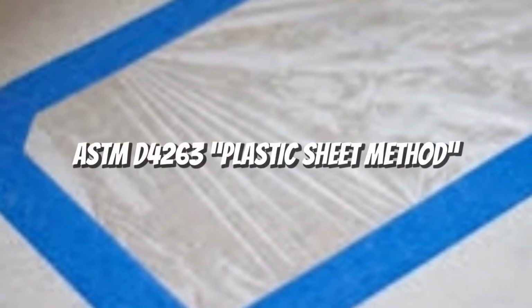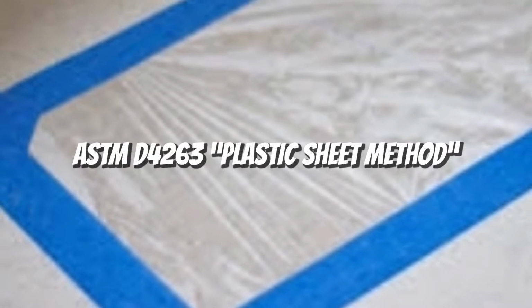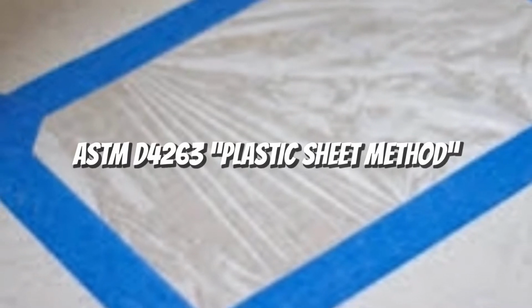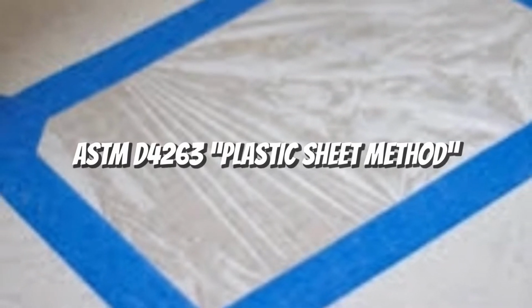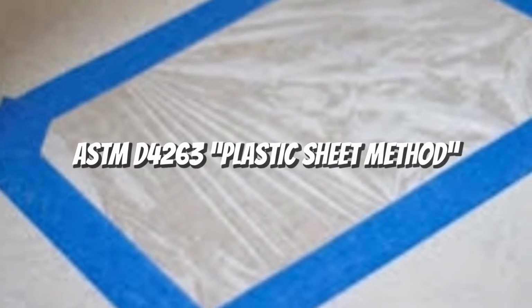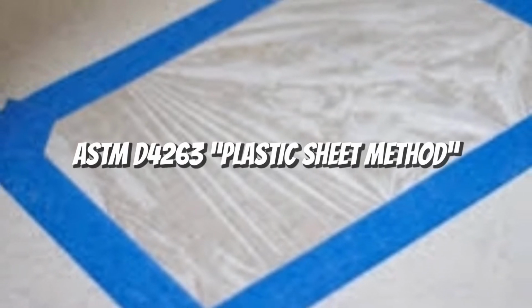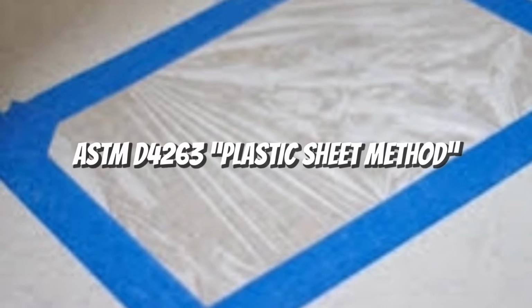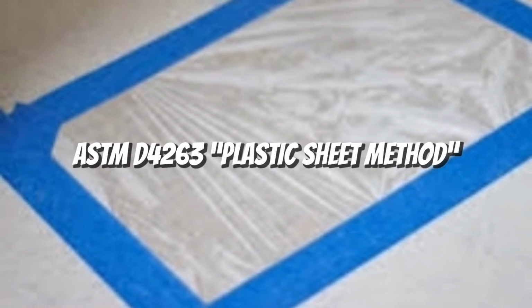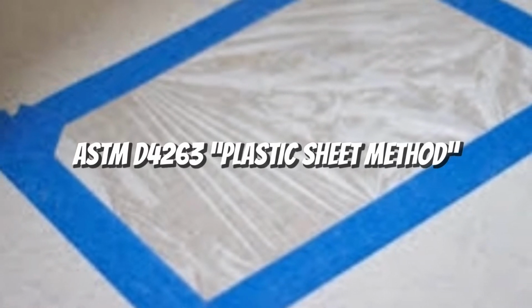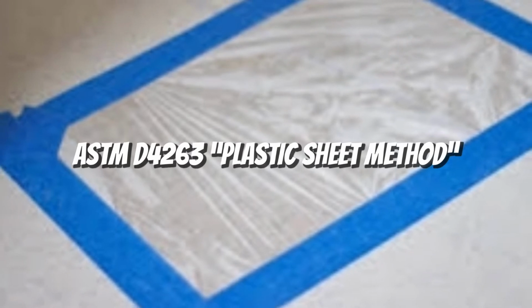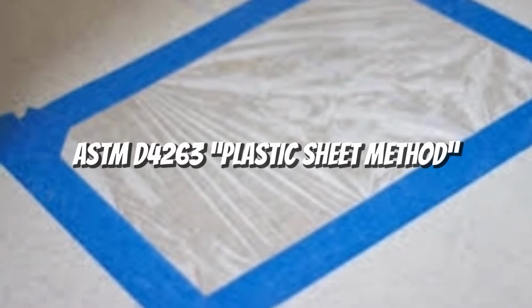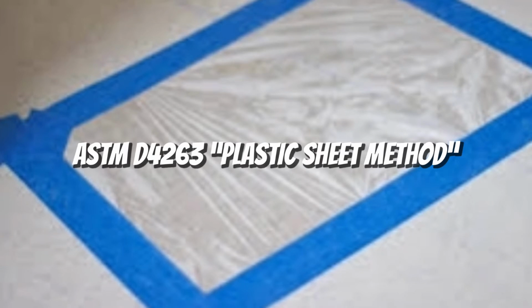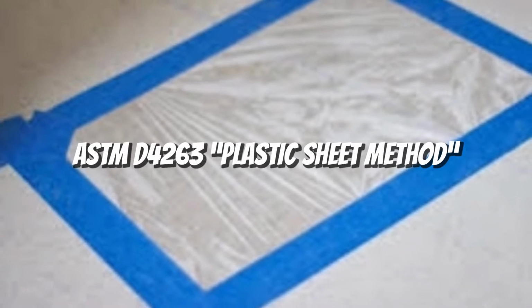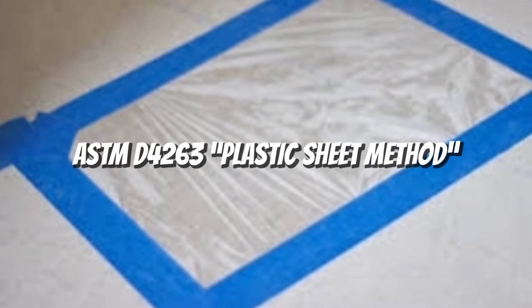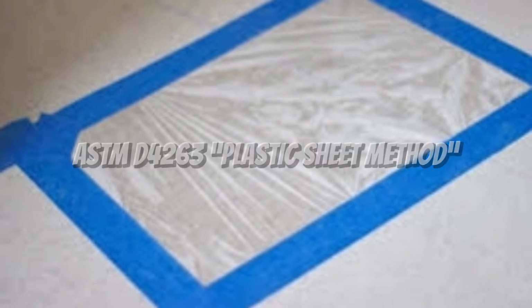ASTM D4263, indicating moisture in concrete by plastic sheet method. This test method involves taping an 18 by 18 inch plastic sheet to a concrete surface and then waiting at least 16 hours. Visible condensation on the sheet or darkening of the concrete indicates excessive moisture. Any coating applied to the surface may be at risk of failure. It's a useful surface level test, but it sheds little light on the severity of the moisture problem within the concrete slab.